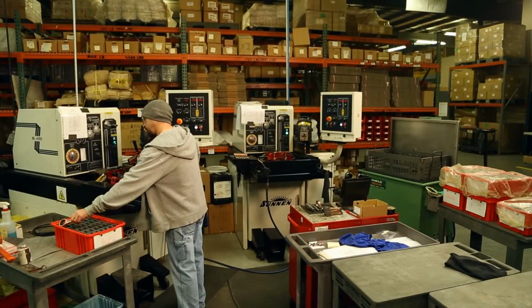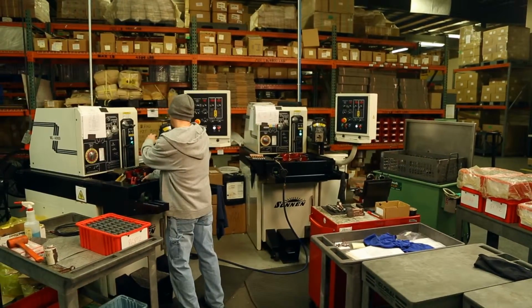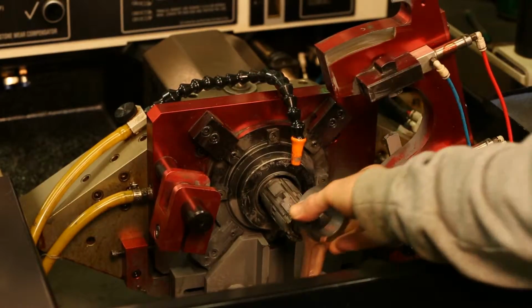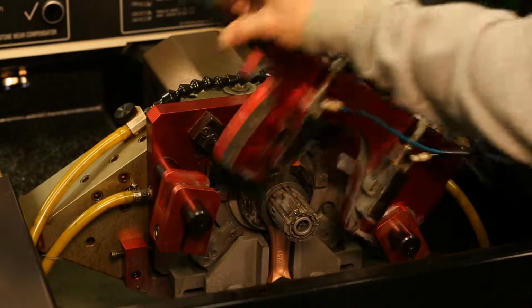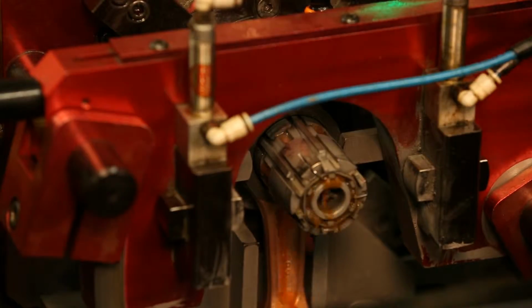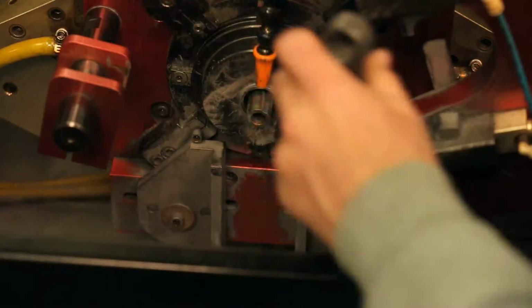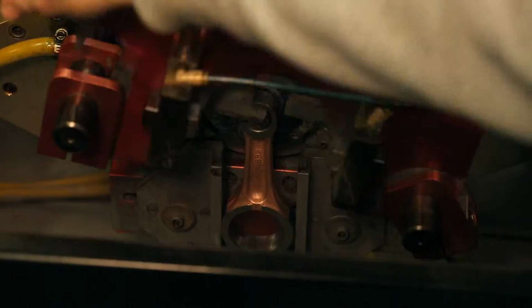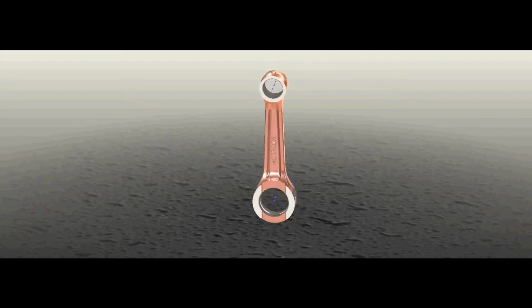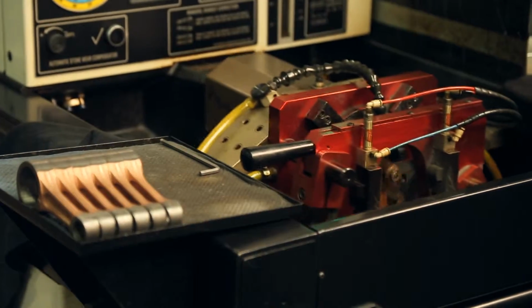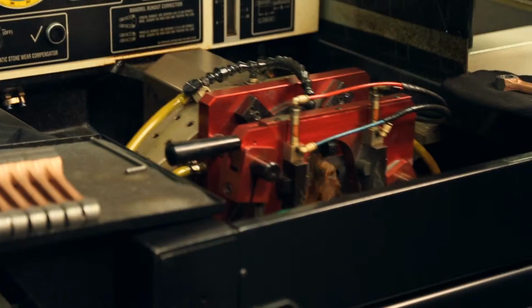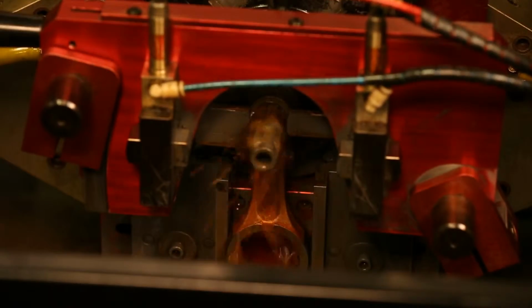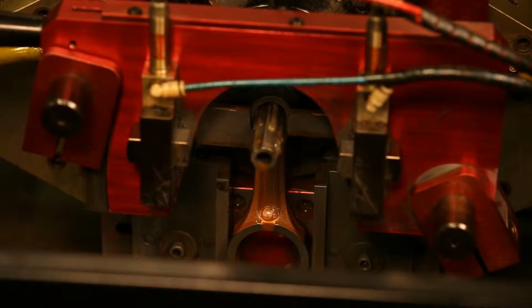Honing the bearing surfaces is the last but very critical machining process. The rods go through 2 honing stations. The first station is for the large bearing hole, and the second station is for the smaller bearing hole. These steps are critical in ensuring a perfectly round, smooth, and perpendicular hole at each end of the rod. The 2 hones smooth the bearing surfaces to within 18 micrometers. This is critical for high RPM use and bearing longevity.